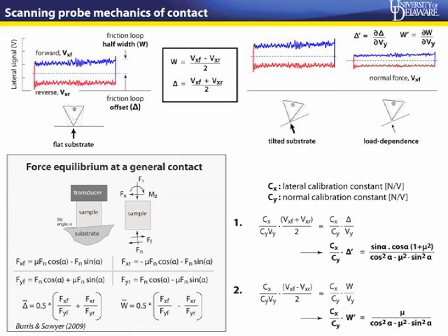If you apply this system of equations to our particular case of the AFM tip contact, with Cx and Cy being the lateral calibration and the normal calibration constants, which allow you to go from volts to newtons, we can basically come up with two analogous expressions which relate this general contact to this particular case of the AFM tip. So you end up with two equations in Cx, Cy. Delta, alpha, remember, is the tilt angle, and mu is your friction coefficient.